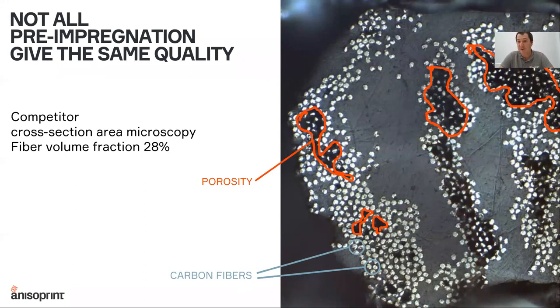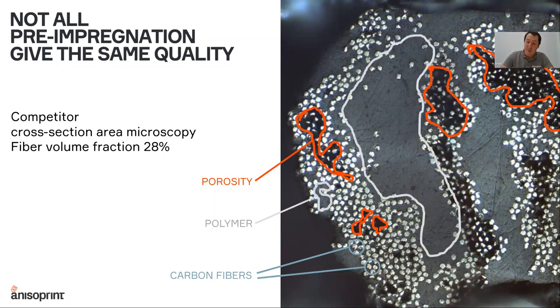It is basically the air pores. So that means that there is no matrix material which bonds together the fibers inside. And you can see that the fibers are not very well distributed. You can see polymer-rich zones where there are no fibers, and you can see that the fiber volume fraction is not too high. So it's less than 30%. It's close to 10% of porosity. And it is actually a very important stage to get good quality.